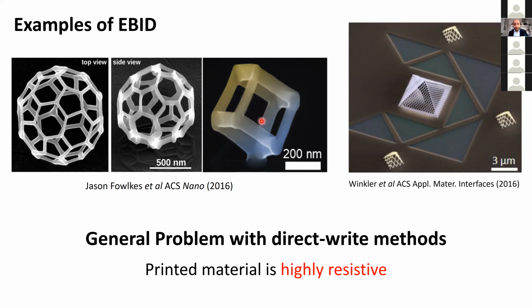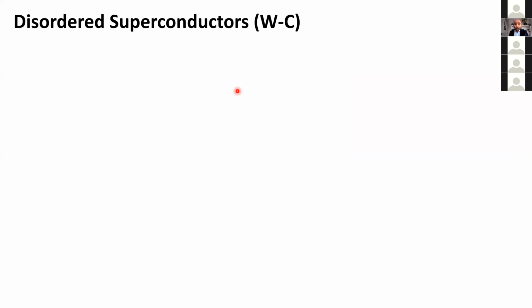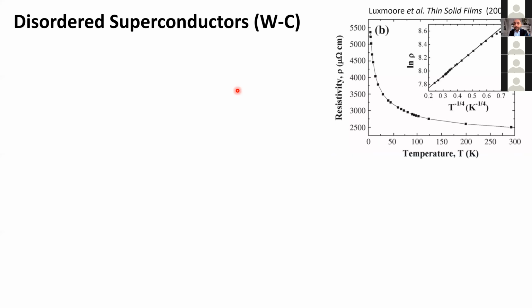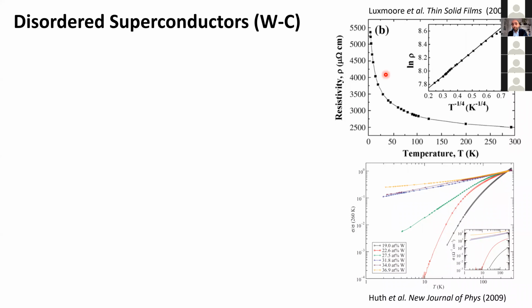And a prime example of that is, of course, tungsten carbide. So you see, tungsten in its pure crystalline form has a transition temperature of about 11 millikelvin. But once you dope it or amorphize it with a lot of carbon, then you can get it to be superconducting at about 5 Kelvin. Now, when they tried to make superconducting tungsten carbide with EBID, well, there were many attempts, and for more than a decade, all these efforts, unfortunately, didn't succeed. So in most cases, they would just have a very resistive system, and the resistance would just go up by lowering the temperature.